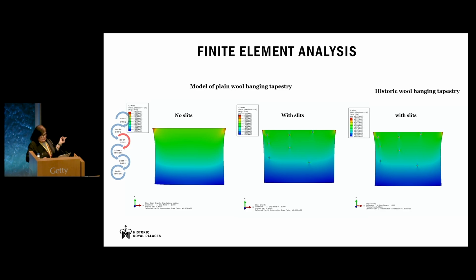The tapestry is constrained across the top level, and we can see on both edges, on the top corners, there is strain building up. The middle figure shows the development of slits, and again, how they behave when we apply gravitational load. And the figure on the right shows the material slightly changed and aged. And in that case, the slits opened up a bit more, indicating that when we have a greater force, then we have more effect in the inherent structural faults of the tapestry.